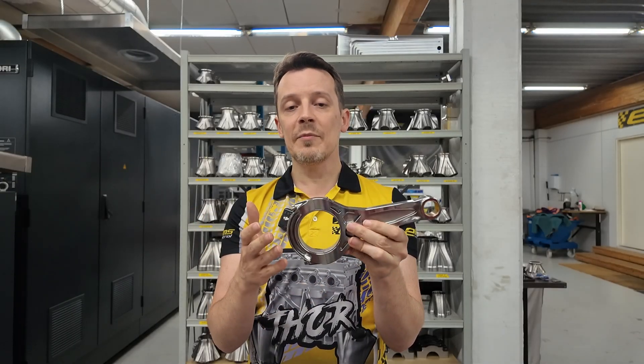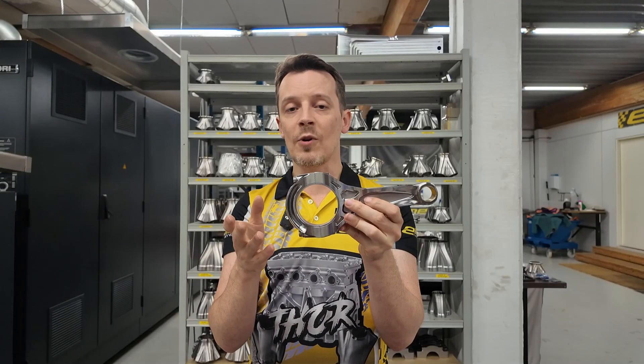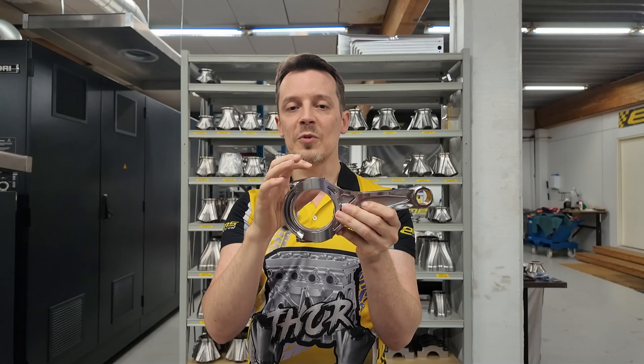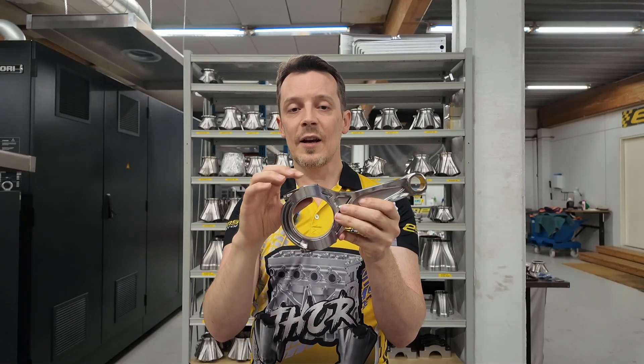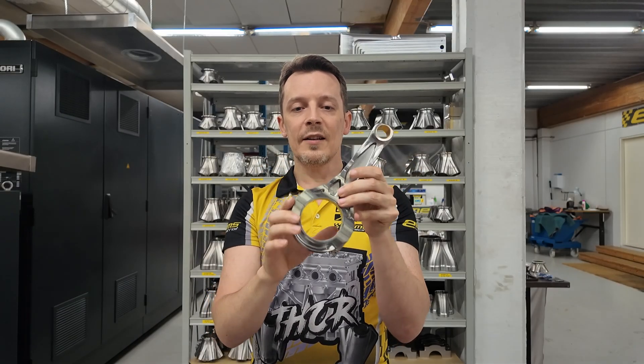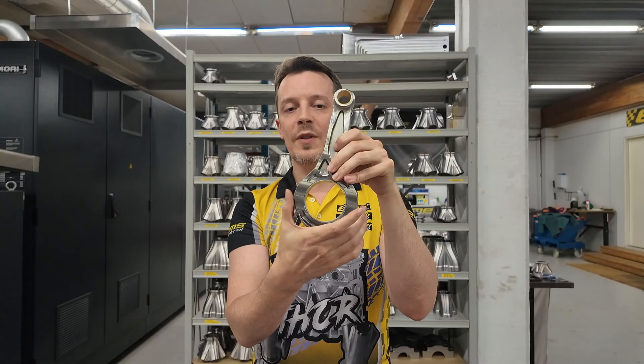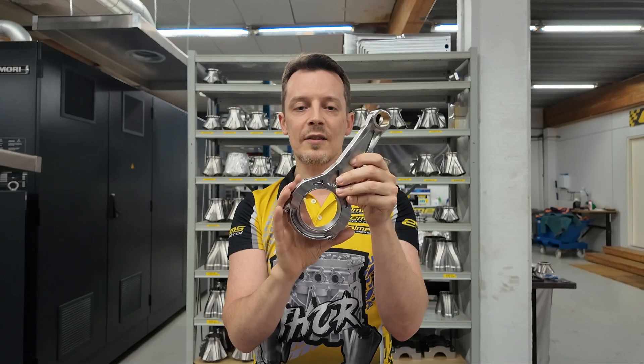However, there are still definite benefits where aluminum rods are much better on the bearings compared to steel rods used past their design forces. With aluminum being much lighter weight, aluminum connecting rods are very, very thick around the big end bearing, which increases geometrical stiffness quite a lot. Especially on valve overlap, where the mass of the piston and piston pin is pulling up on the connecting rod, you don't end up with the pinching effect as much with an aluminum rod compared to a steel rod. This has been taken into consideration with the titanium rod design.